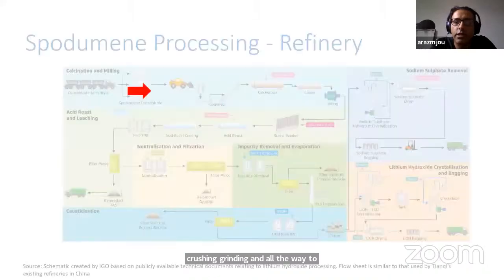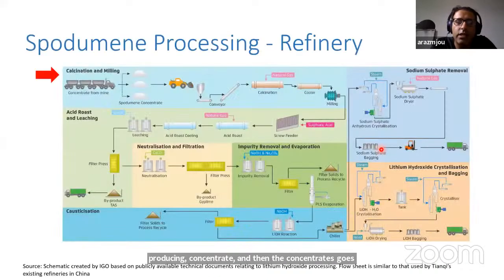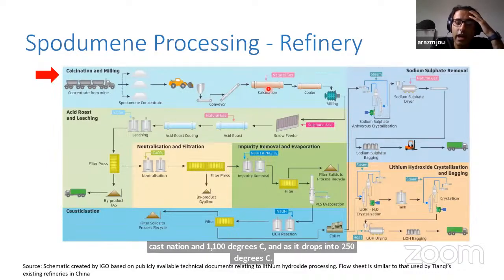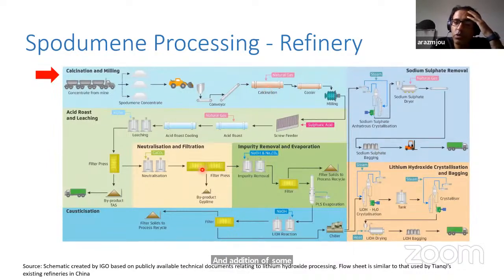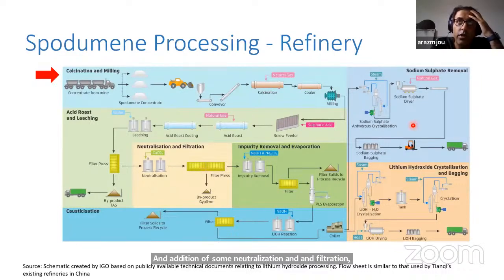This is a typical flow sheet of hard rock spodumene mining. It starts from mining, crushing, grinding, and all the way to producing concentrate. Then the concentrate goes to the refinery process, which involves calcination at 1100 degrees C, acid roasting at 250 degrees C, and addition of neutralization, filtration, impurity removal, and finally producing lithium hydroxide. It's a typical lithium hydroxide or lithium carbonate production flow sheet.